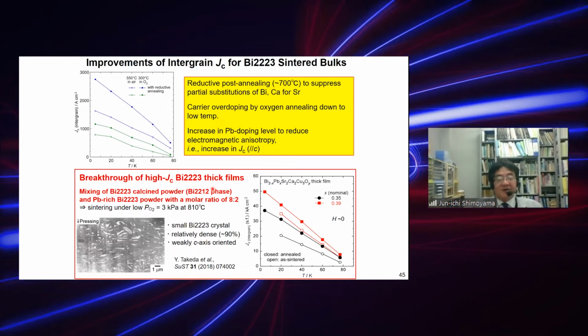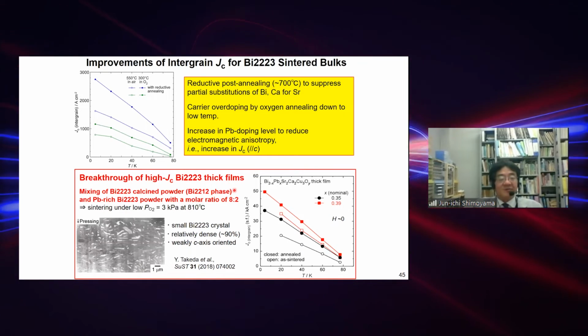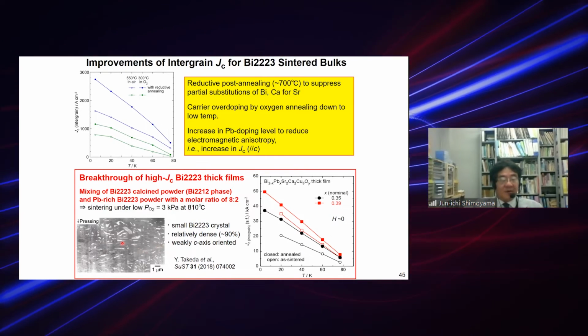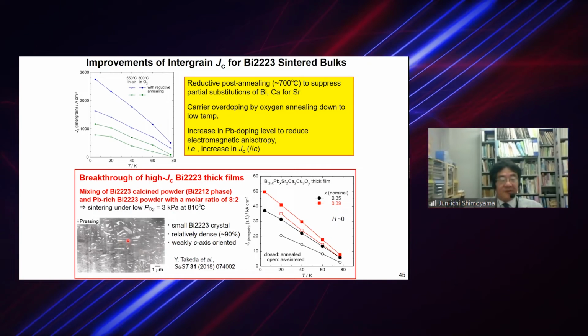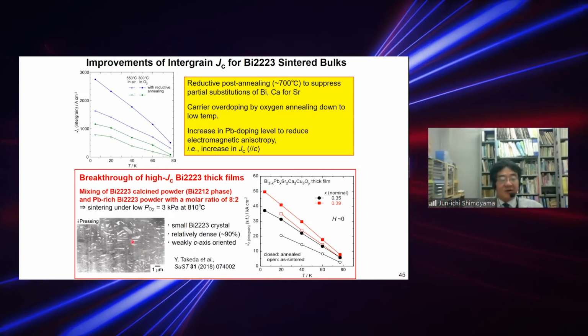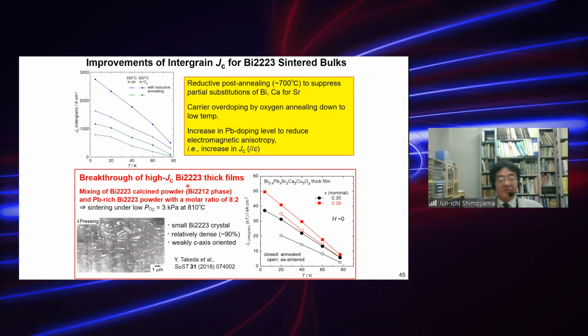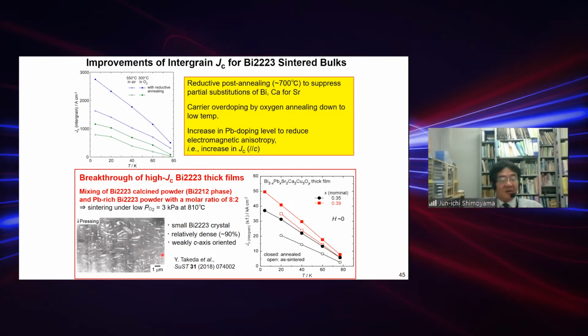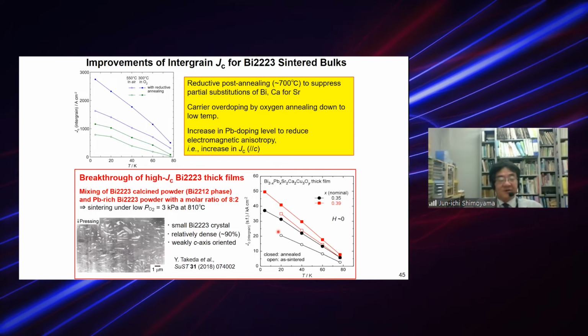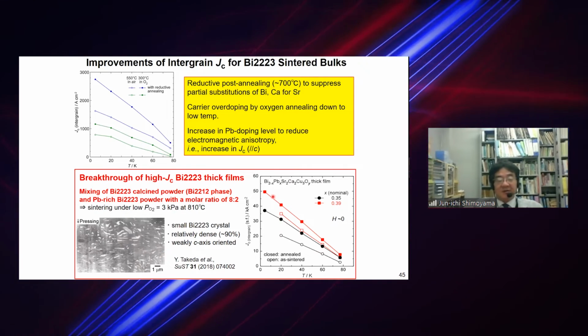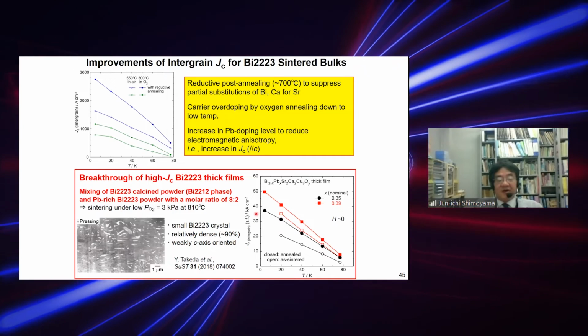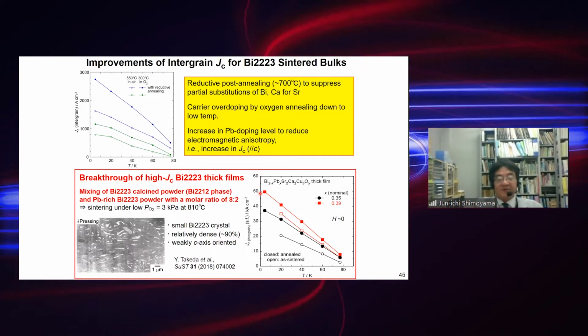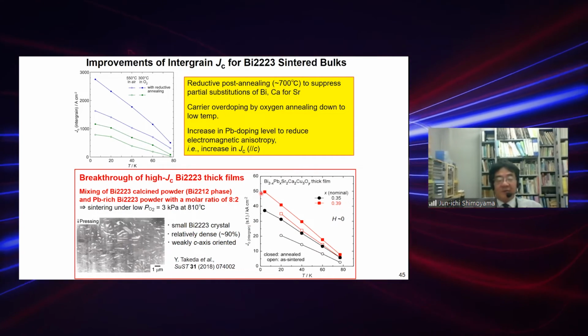So to prepare a superconducting joint with high Ic for Bi-2223 tapes, at the beginning we developed very high Ic Bi-2223 thick films, as you see here. By pressing, we can prepare slightly c-axis-oriented thick films of the Bi-2223 layer, and this thick film can carry large current, as you see here, Jc of 50 kiloamps per square centimeter at 4.2 Kelvin.